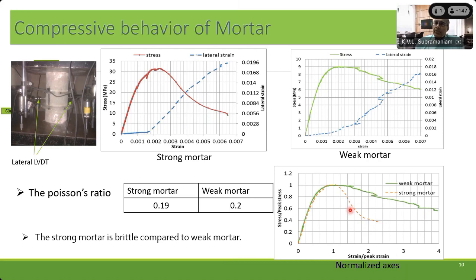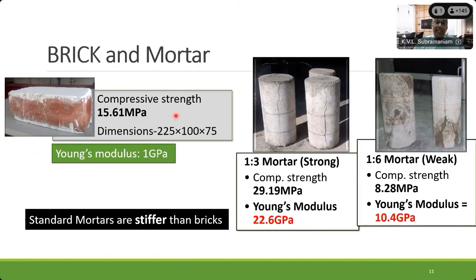Now, the reason for trying these two mortars is very straightforward. The stronger mortar is what I would expect to get in the cities, where we are perhaps a little bit more conscious and we are using more cement, whereas the weaker mortar is what you may expect to see in the villages, where they skimp on the cement and the quality of cement is not so good. So the compressive strength of the mortar is also going to be much lower. Now, the brick that we sourced had a compressive strength of 15.6 MPa. This is my strong mortar, which is 1:3, which is basically 1 cement to 3 sand. And the weaker mortar is 1:6 mortar, where you have 1 cement to 6 sand.